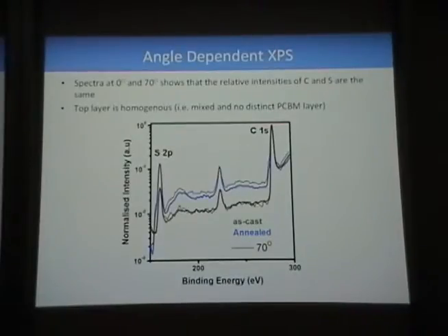Also, at the same time, one of the nice techniques about XPS is that you can do angle-dependent measurements. So we take the spectra at 0 degrees, which is a sample sitting flat, and at 70 degrees with the sample tilted at a large angle. And at 70 degrees, you can improve the surface sensitivity. And now here, what you see is that the relative intensities of the contribution from the carbon and the sulfur are the same at both angles.